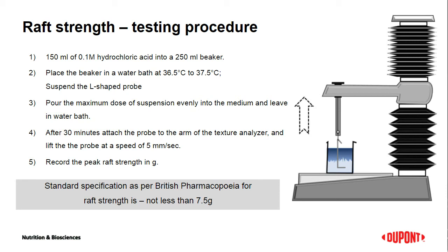After 30 minutes, the beaker along with the probe is removed from the water bath and the probe is attached to the texture analyzer. The raft strength is measured by lifting the probe at a speed of 5 mm per second. The raft strength is recorded in grams, and the minimum raft strength required as per British Pharmacopoeia specification is not less than 7.5 grams.